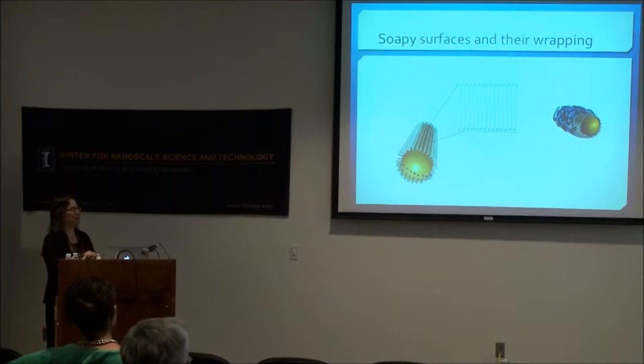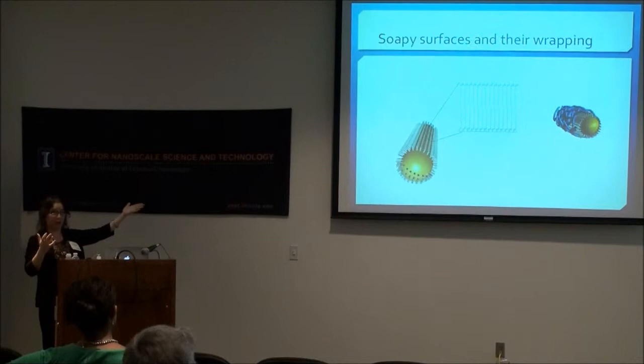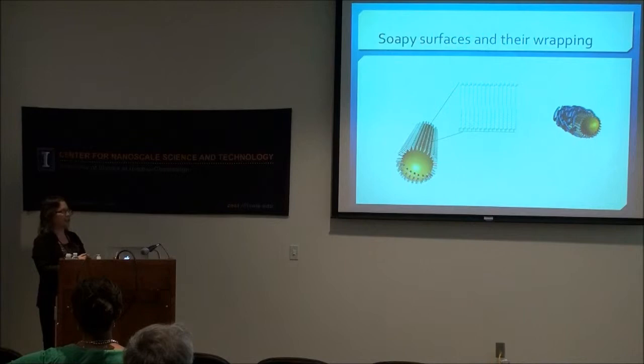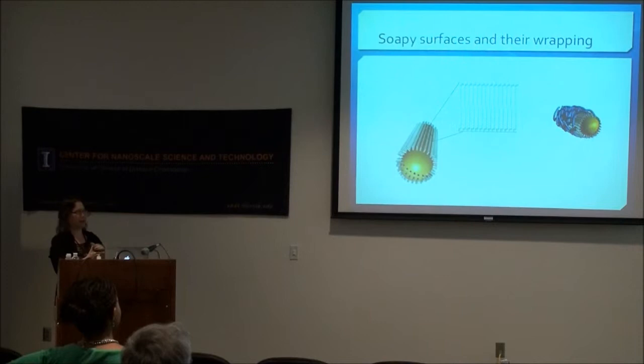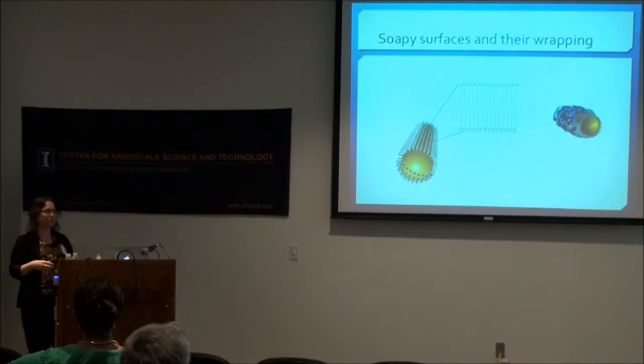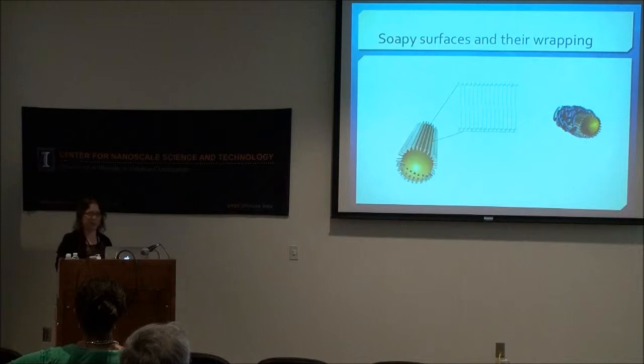If a cell sees these particles, it sees a bunch of quaternary ammonium groups. To functionalize the surface, our favorite approach is a wrapping procedure: we take a polyelectrolyte of opposite charge to our particle and incubate it at the correct molecular weight. We can add layers and layers onto our particles and terminate with functional groups to attach things such as targeting molecules.